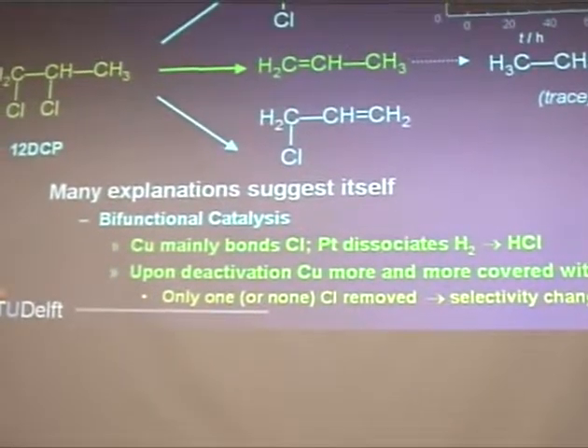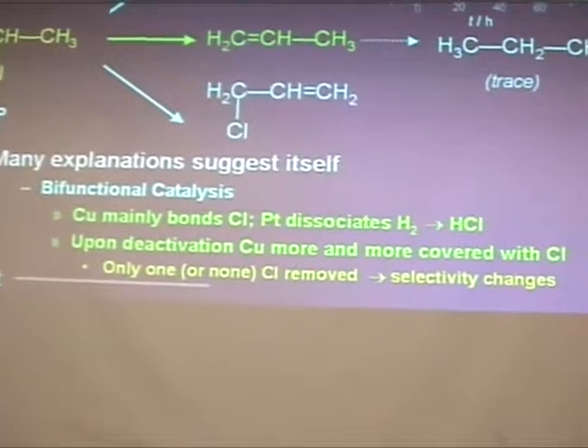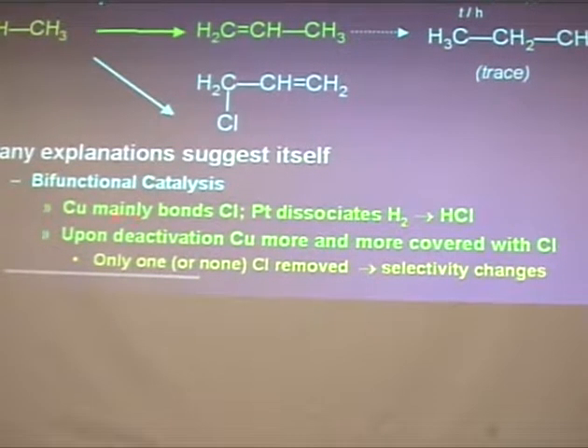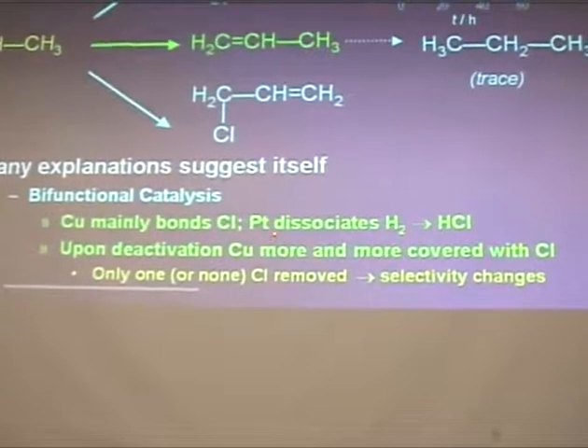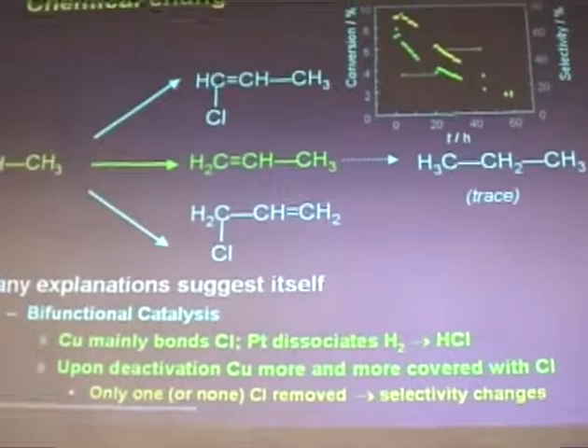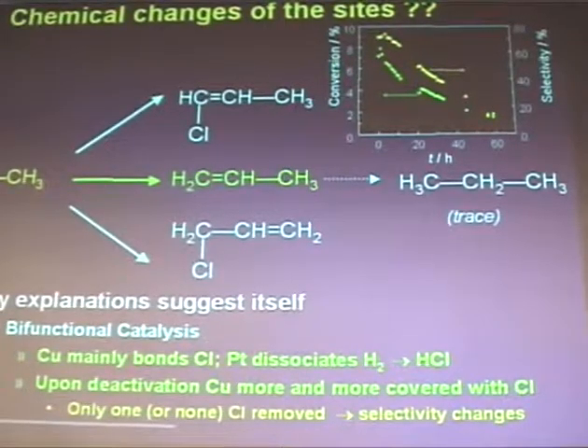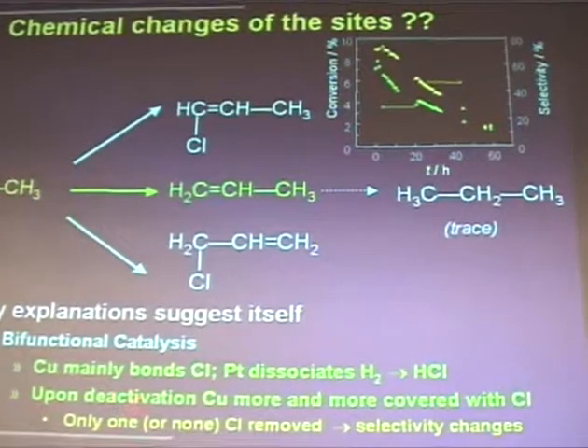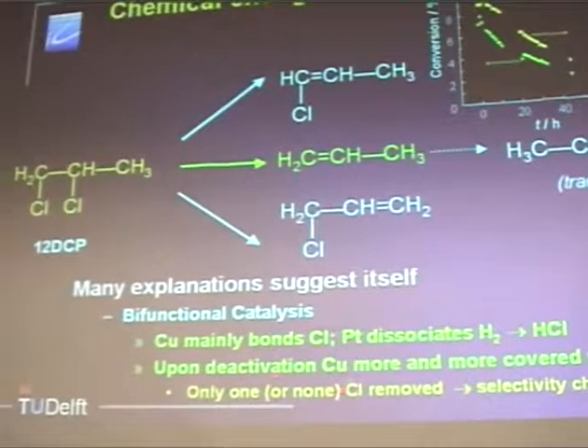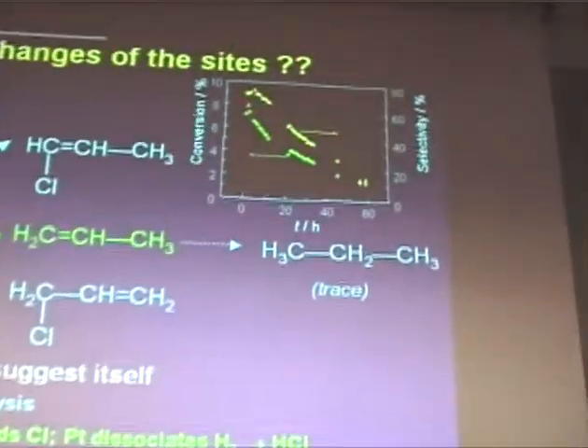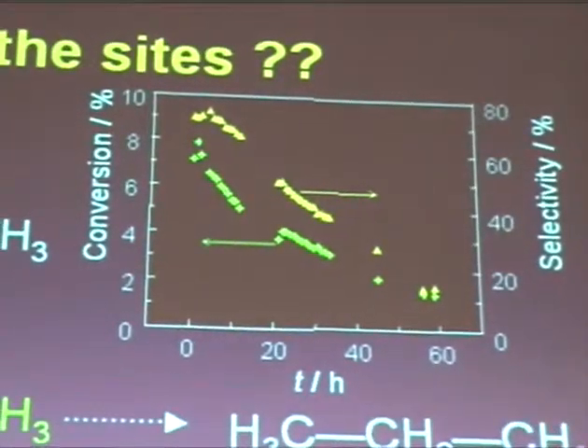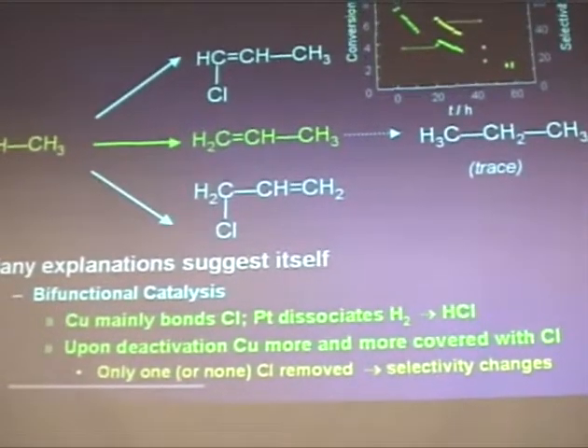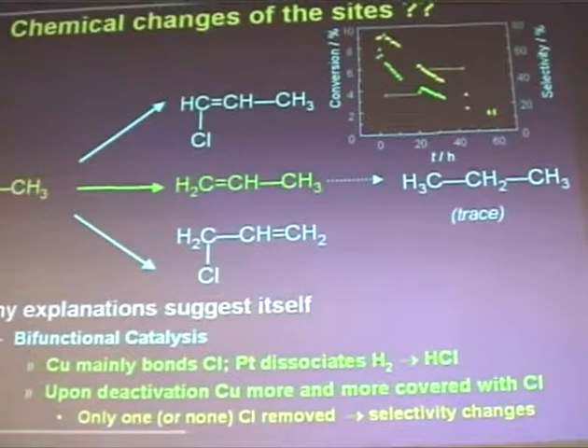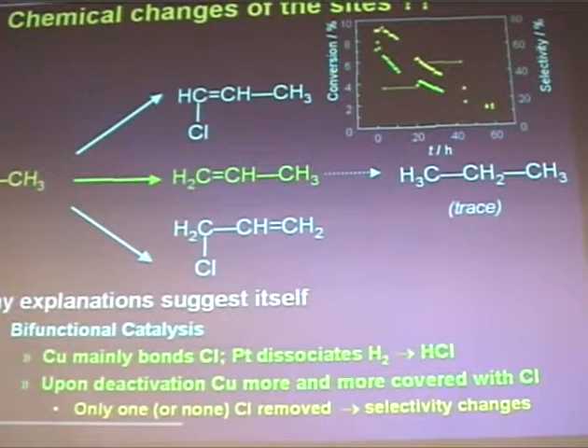So first, the chemical changes, what could it be? Well, I think myself it could be true that you perhaps have the model that the copper binds the chlorides. Platinum dissociates H2, and via a kind of spillover the H goes to the chloride and removes it as HCl. When you deactivate, the platinum will be deactivated, absolutely, and the copper will not be freed anymore of the chloride, and you have too much chloride, and the copper might have only 1 chloride, or none. And I think that explains it.